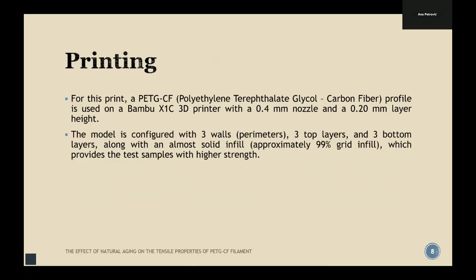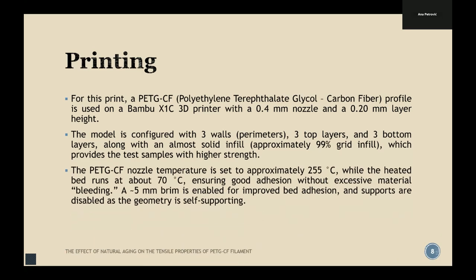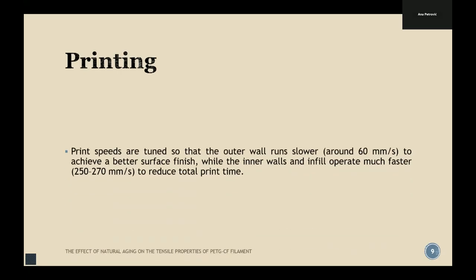The model is configured with three perimeters, so it's 3 walls, 3 top layers, and 3 bottom layers, along with almost solid infill, 99% infill, which provides the test sample with higher possible strength. The nozzle temperature is set to approximately 255, while the heated bed runs at about 70 degrees Celsius, ensuring good adhesion without excessive material bleeding. An approximately 5 millimeter brim is enabled for improved bed adhesion, and supports are disabled as the geometry is self-supporting, printing flat on the table.